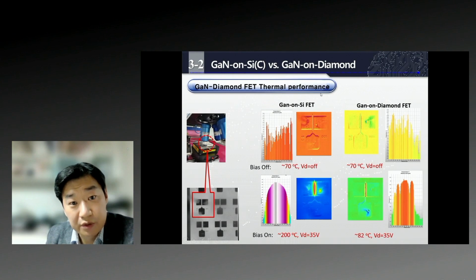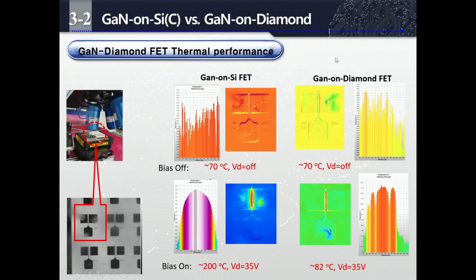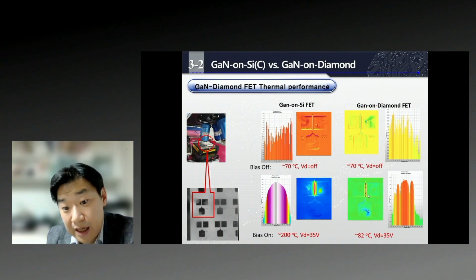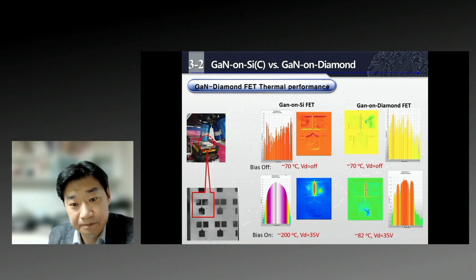This is the result for the GaN on silicon and GaN on diamond FETs. Without bias, GaN on silicon and GaN on diamond are at a similar temperature, 70 degrees Celsius. But after bias on, with a drain voltage of 35 volts, GaN on silicon reaches 200 degrees Celsius, with a hotspot zone here. But GaN on diamond dramatically reduces the junction temperature, up to 82 degrees Celsius.